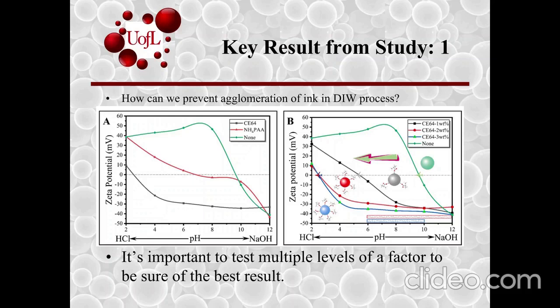And what I learned from this one is that it's important to test multiple levels of a factor to make sure it's the best result. So you can see they do exactly that here. They don't just test 1% and 2%, but they also test 3%. Because if they didn't test 3%, they wouldn't know that maybe 3% is better than 2%. You can see as well in the graph labeled B, that little red and blue rectangular sections at the bottom show the stable sections, and they can see that after 2%, the stableness decreases. So they know that 2% is in fact the best option.